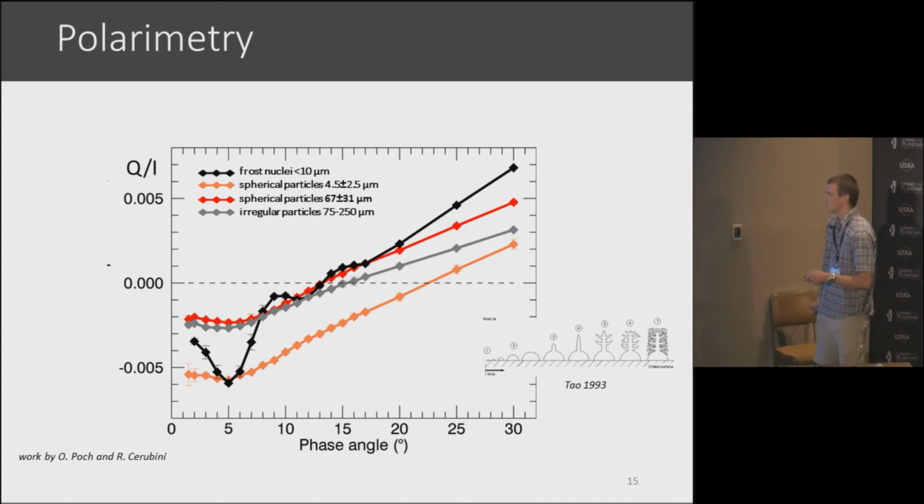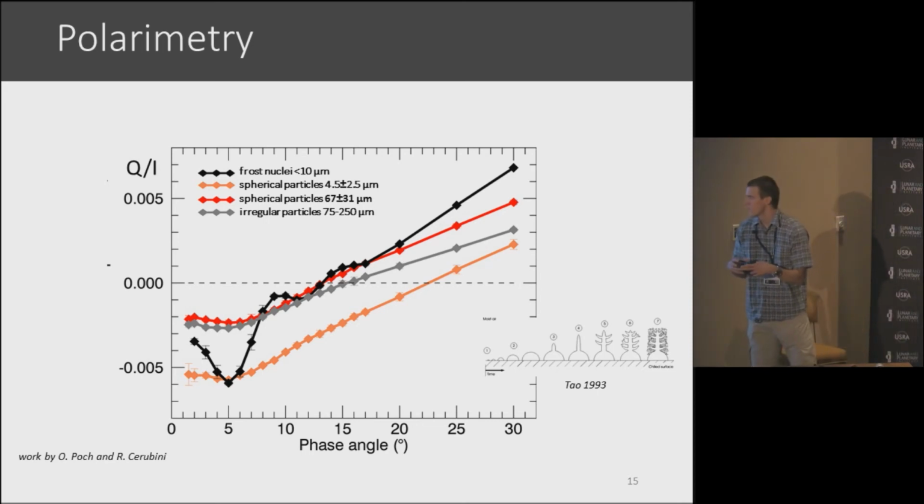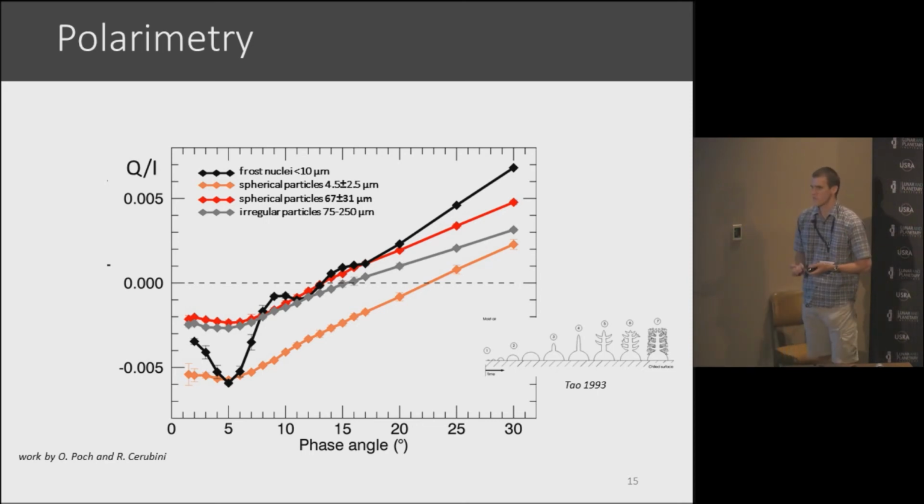Frost condensates are more or less transparent, while flash-frozen liquids have impurities. And these impurities prevent this glory effect, because the liquid starts to freeze on the outside and freezes towards the center, thus creating stress and fracturation inside the particles, making them more opaque.